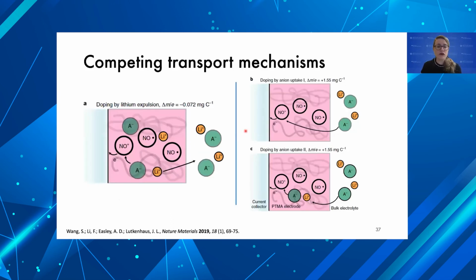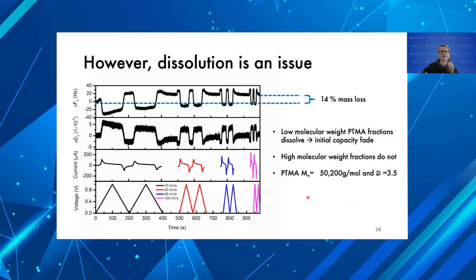To give you a view of that, when we have lithium cations expelling, it's because we already have electrolyte in the swollen polymer cathode, and an anion locally dopes the oxoammonium cation, and for balance, the lithium cation has to come out. And then when we go into the anion uptake region, the anion from the bulk electrolyte is coming in. Okay.